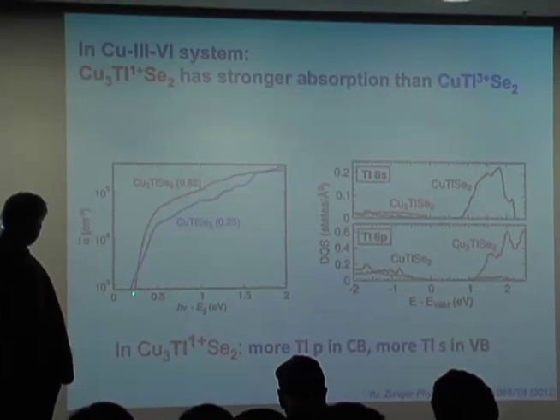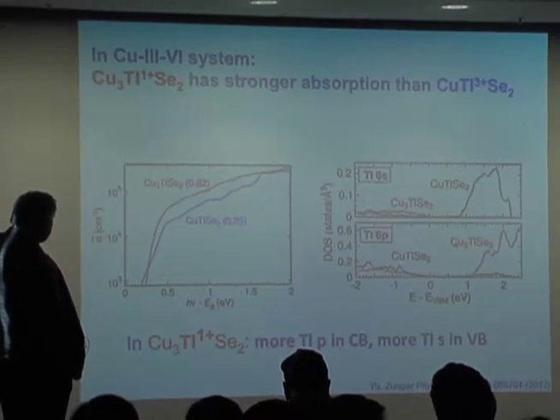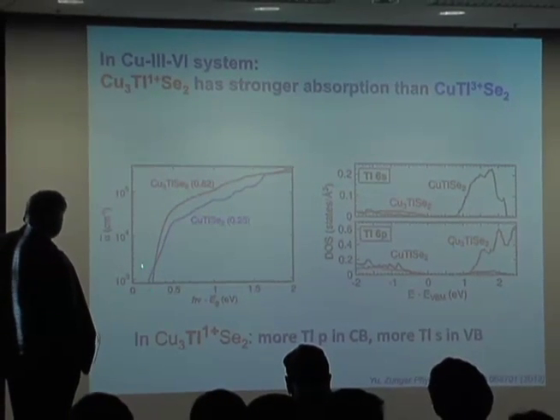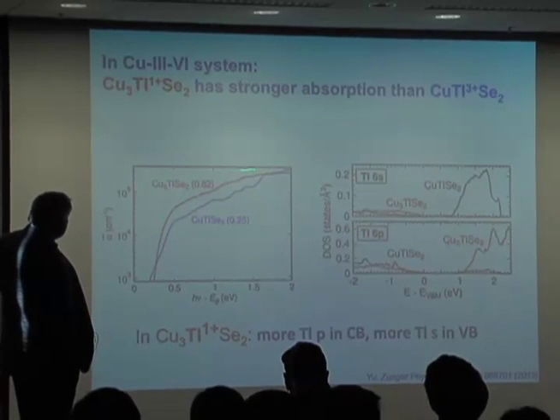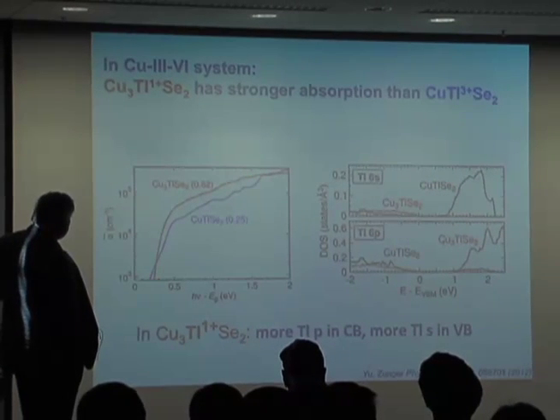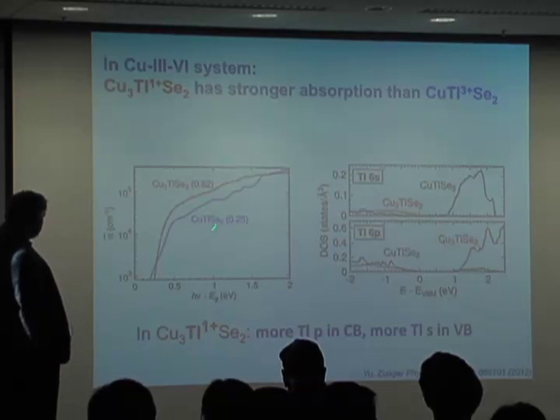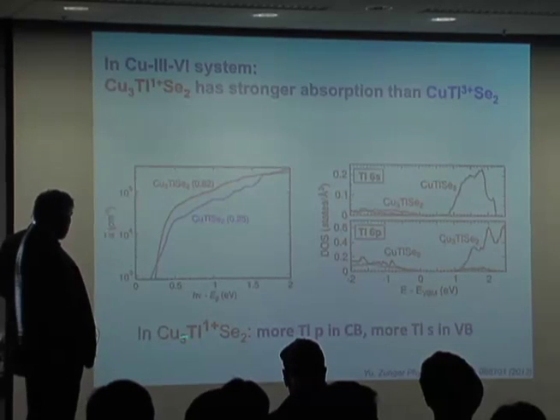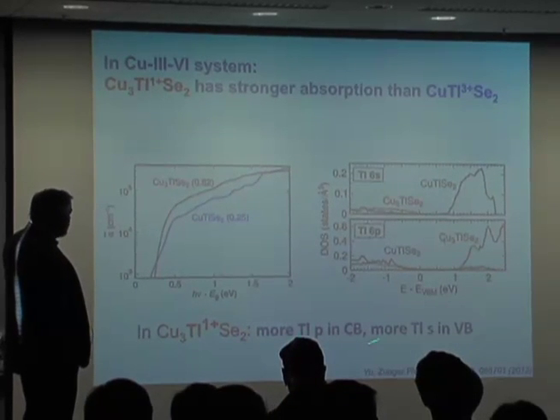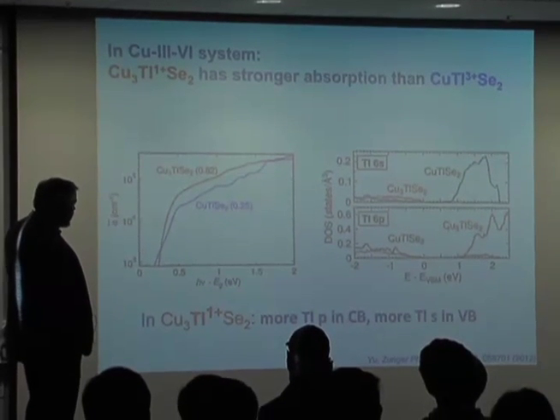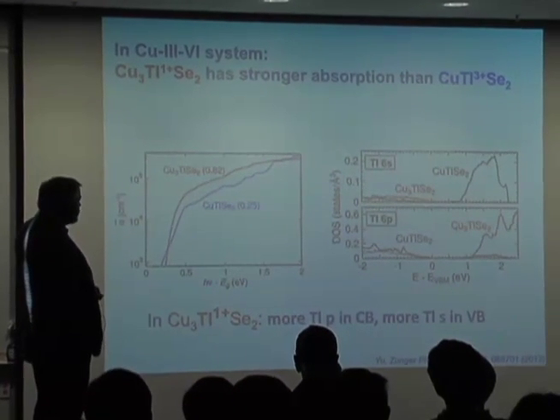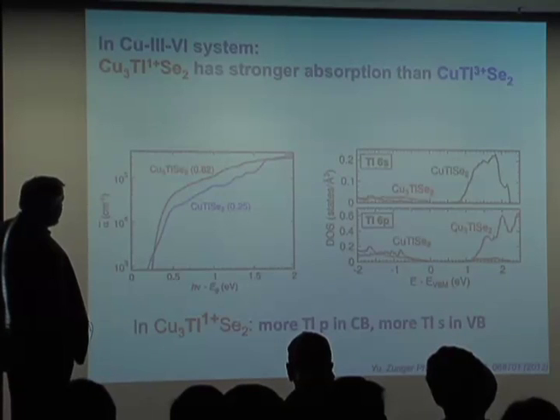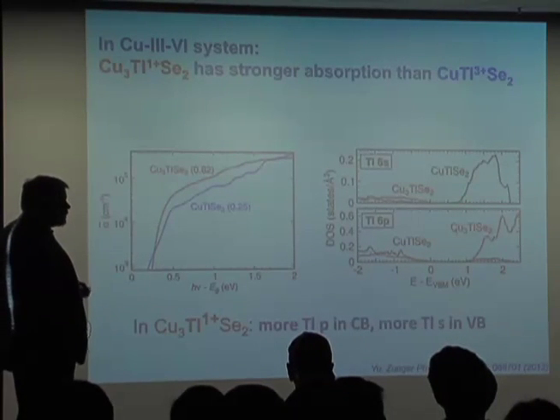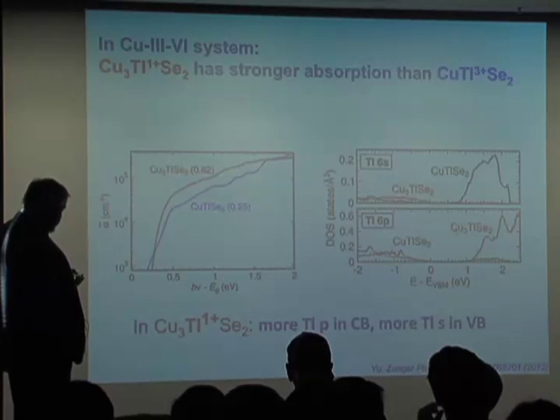And in fact, if you look at the calculated absorption spectra, we actually find that the valence 1 absorption spectrum has stronger absorption than the valence 3 absorption spectrum. And in fact, what we think is that there's a lot more P in the conduction band and a lot more S in the valence band that gives you a higher overlap of density of states for that absorptivity. So we wanted to probe that more experimentally and theoretically, not just theoretically.